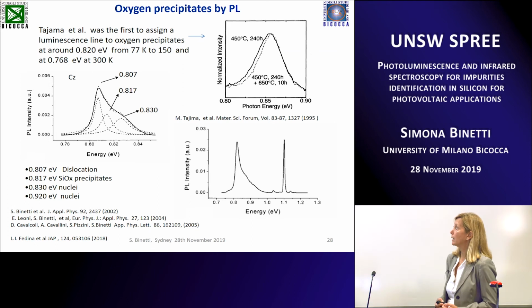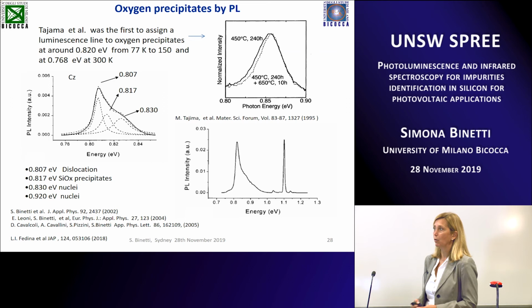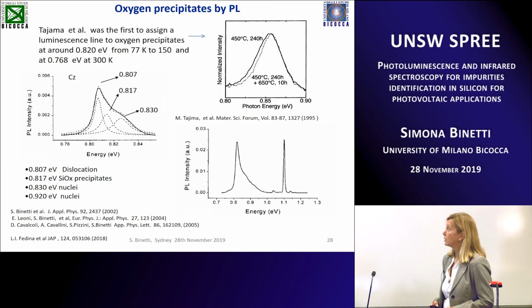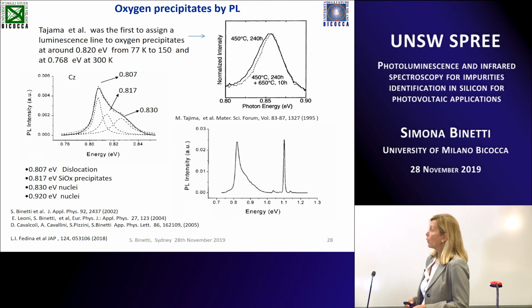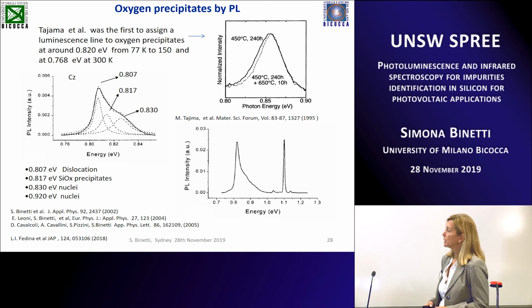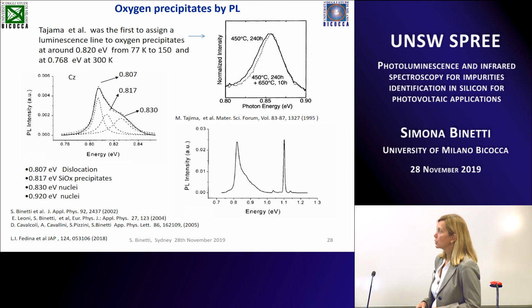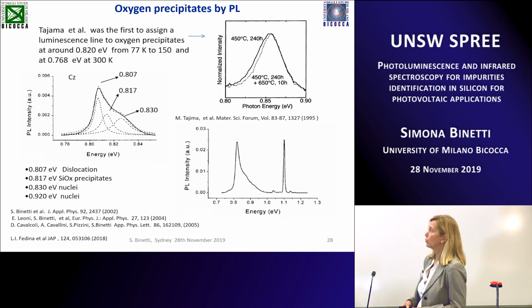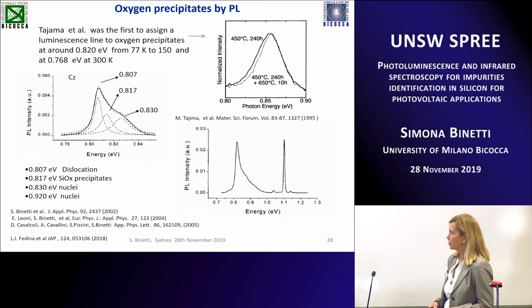And also we have done a big work on plastically deformed silicon in order to make a correlation between the type of dislocation and the D1, D2, D3 bands. And now we can say that you can distinguish between dislocation and oxygen precipitates just by looking at lower temperature at the position of the bands. So we can distinguish between dislocation, silicon dioxide large precipitates, and also nuclei and early stage of oxygen precipitation.